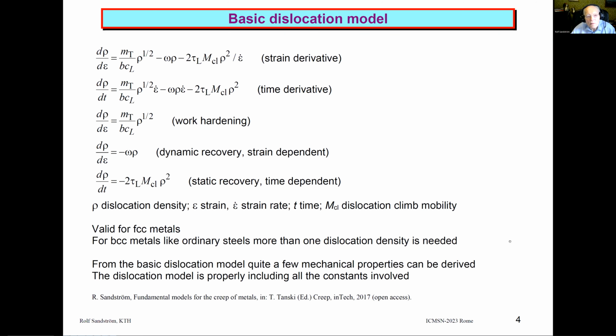The starting point for many of the mechanical properties is a basic dislocation model. It consists of 3 parts. It's a work hardening part describing the continuous increase of dislocation density with increasing strain. But there are also recovery parts, which take into account that dislocations are interacting and annihilating each other. There's a dynamic recovery part, which is strain dependent, and a static recovery part, which is time dependent.